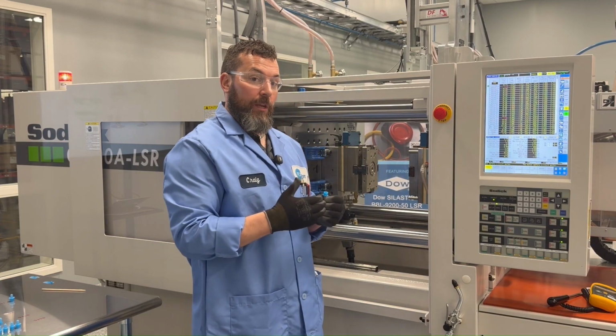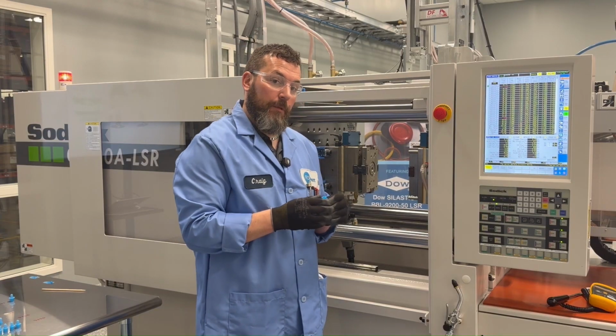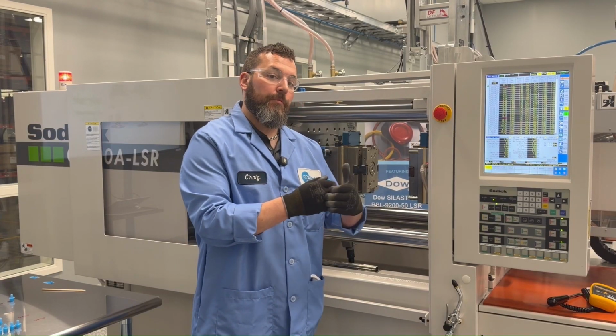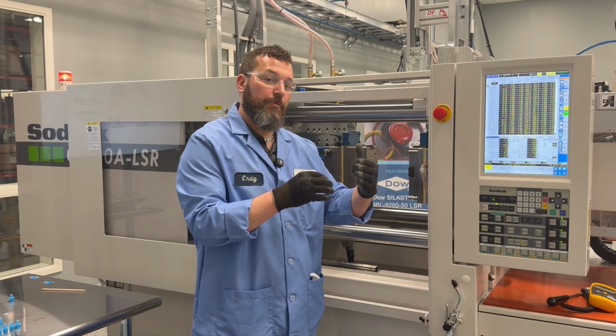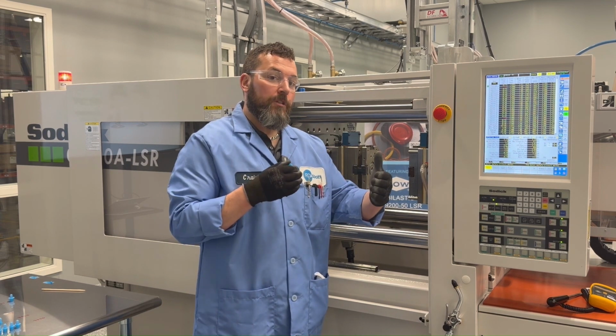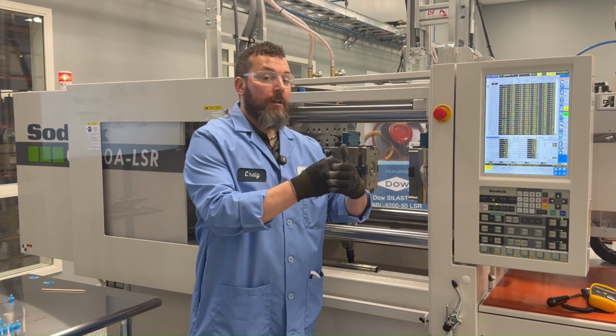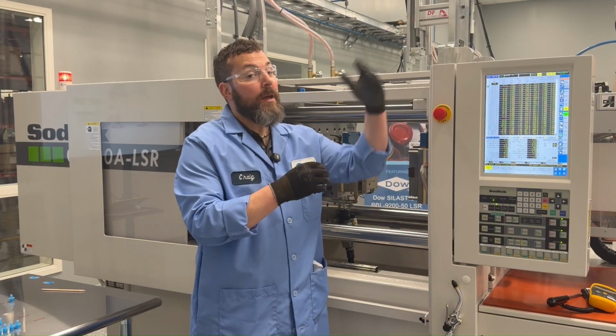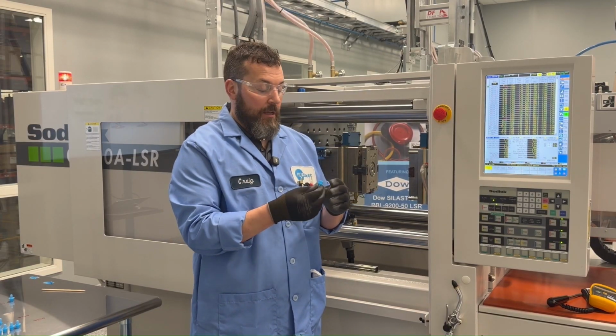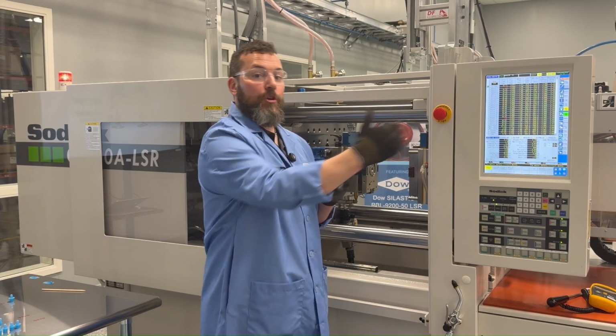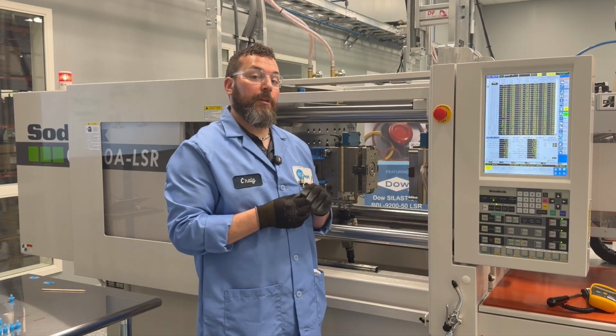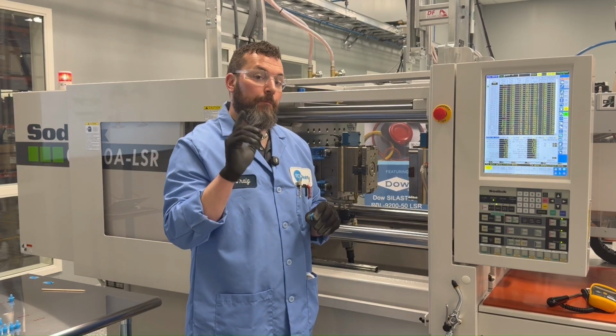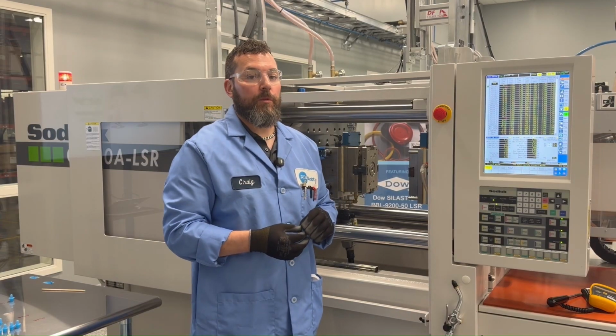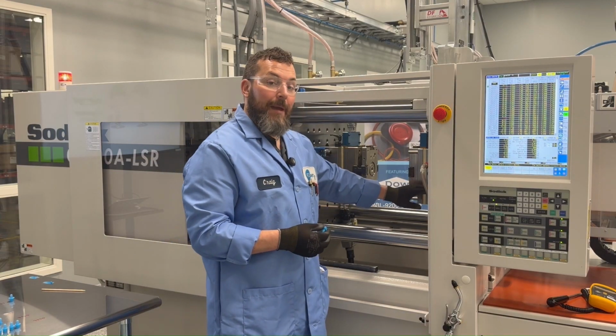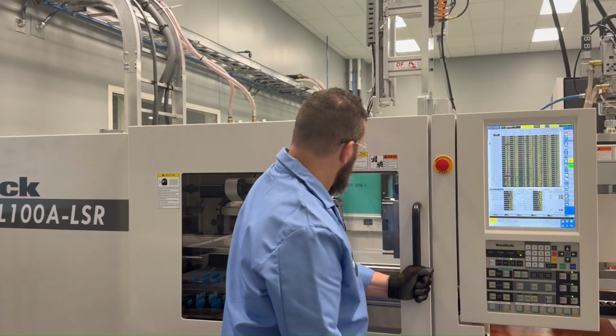How fast are we injecting? How hard are we pushing that material? Remember, LSR is compressible. We like to say upwards of 7%, but we put a force behind that and push. We can compress this material a little, way past 5 to 7%. So how much is that plunger pushing back? How much pressure are we putting on the manifold? And that's something important that you always want to discuss with the mold maker. What is the max limit of that manifold?